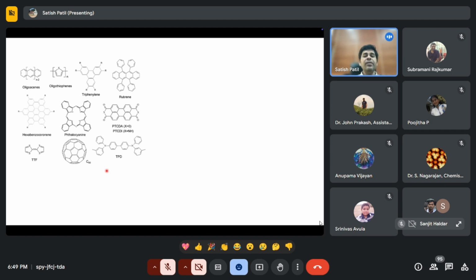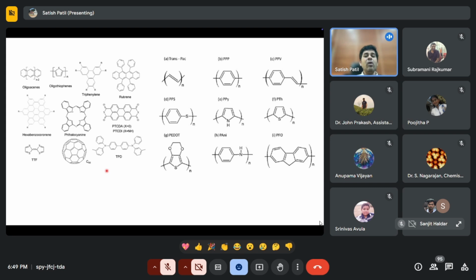There is another category which works in polymers. So organic semiconductors are divided into two different classes. One is small molecules, a range of derivatives, as you see. And you can polymerize some of these molecules and make large, gigantic molecules. So polymers. And what is the major difference now? In terms of properties, they differ significantly. For example, with small molecules, it is difficult to cast a thin film from solution, because the viscosity of these molecules is not as high as polymers. So these materials we have to thermally evaporate to make a semiconductor grade thin film.